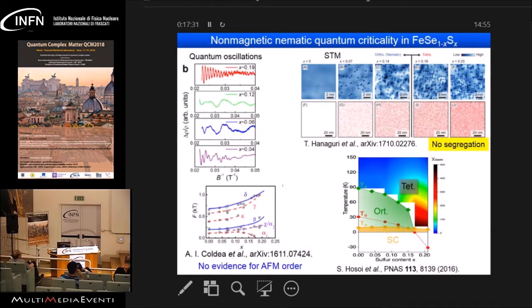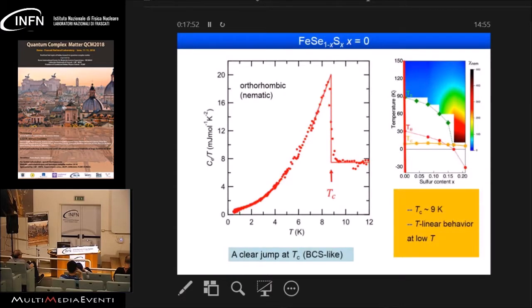And also, we have observed quantum oscillations in a wide range of the sulfur content, meaning that we have very clean crystals. So I think this is a quite good system, homogeneous and clean, to look at this BCS-BEC crossover physics. So let's look at the specific heat data as a function of x. So again, this is the iron selenium, so x equals 0. So in this phase diagram we are looking at here, we are deep inside the nematic phase.